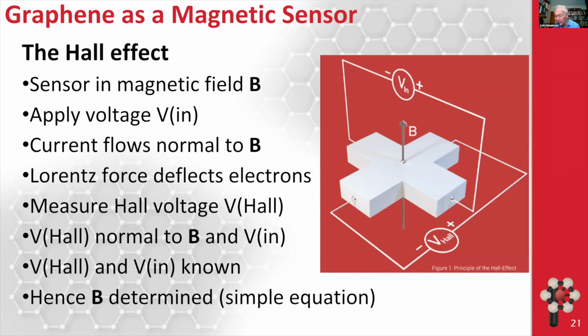I think you all know about the Hall effect, and I'm looking at my watch, so I need to speed up. The Hall effect very quickly is in this diagram. The cross that you see is the material. Many people use silicon, the most common material. We're using graphene in the shape of this cross. You have a magnetic field perpendicular to the plane of the graphene. Then you apply a voltage at right angles to the magnetic field. What happens is there's a Lorentz force on the electrons that run through this material because you've applied a voltage. The magnetic field puts a Lorentz force on, which moves the electrons sideways, and you generate a Hall voltage in the other perpendicular direction.